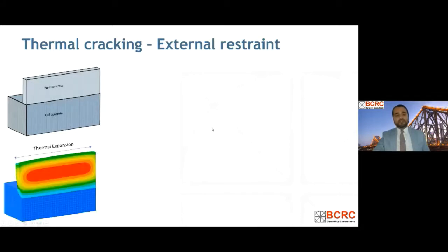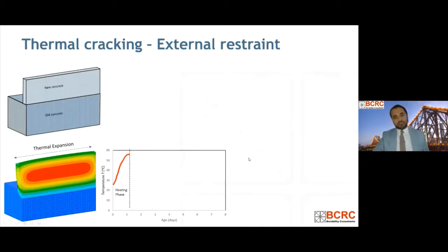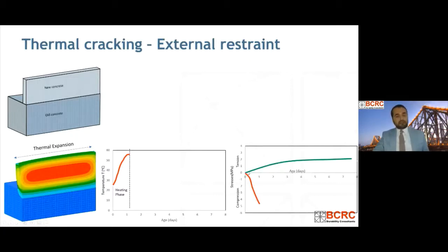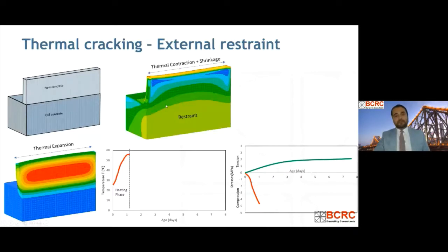What happens during the heating phase is that it expands, right? The temperature goes up, and as it expands, compressive stresses develop in the concrete, right? And concrete is strong in compression, so there should be no issue at that stage, and this is the tensile strength development with age. But in the cooling phase, thermal contraction is occurring, and at the same time we have some shrinkage, which is likely to be autogenous shrinkage at that stage, right? So this is the cooling phase.